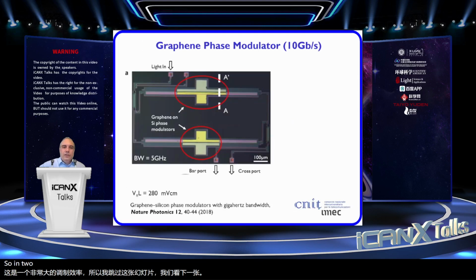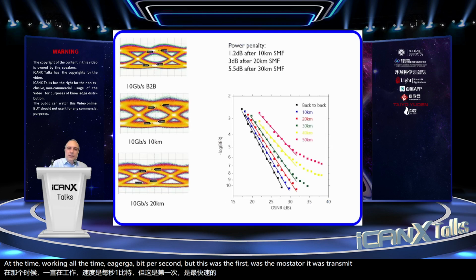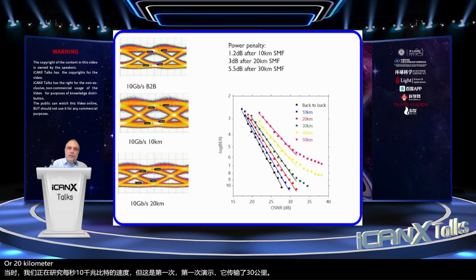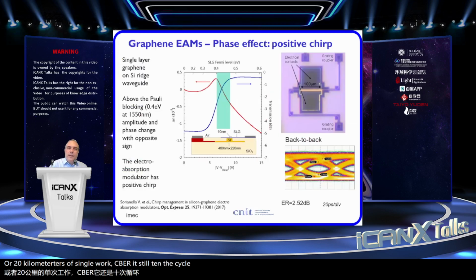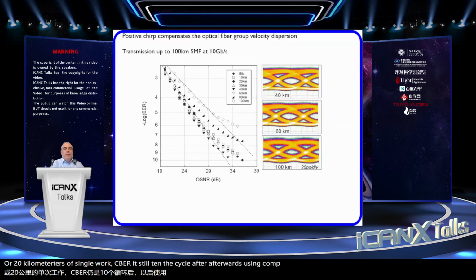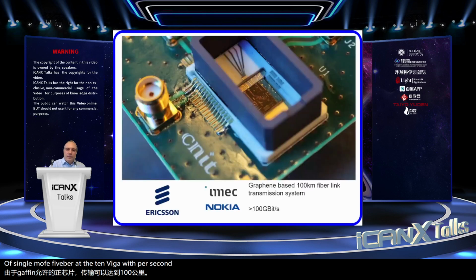So in 2018, we realized, together with CNIT and IMEC and others, the first graphene phase modulators, at the time working only at 10 gigabit per second, but this was the first demonstrator. It was transmitted over 20 or 30 kilometers of single mode fiber, still at 10 gigabit per second. Afterwards, using compensation of the positive chirp that graphene allows, the transmission was done up to 100 kilometers of single mode fiber at 10 gigabit per second. And a few years ago, together with IMEC, Nokia, Ericsson and CNIT, we produced this fiber-based link modulator working at over 100 gigabit per second.